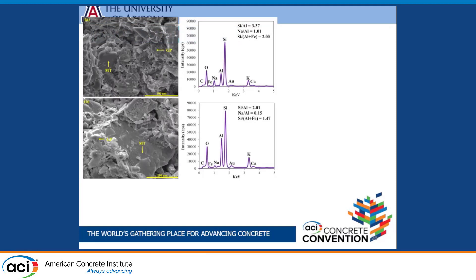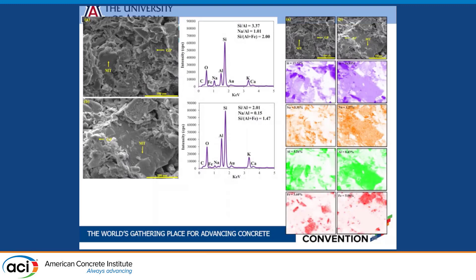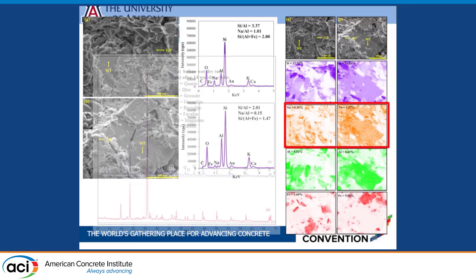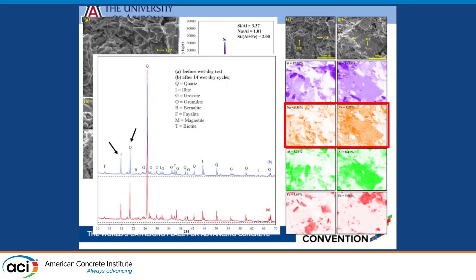Microstructure analysis showed that after 14 wet-dry cycles, permeability and void ratio increased. From EDX mappings, sodium was the element washing away from the surface, where geopolymerization is less stable — the core of broken samples remained very stable. Unreactive sodium washing away is the main reason for the increased void ratio. XRD analysis from zero and 14-day wet-dry cycles showed a reduction of quartz peaks and increasing albite, indicating transformation of quartz to albite during wet-dry cycling.